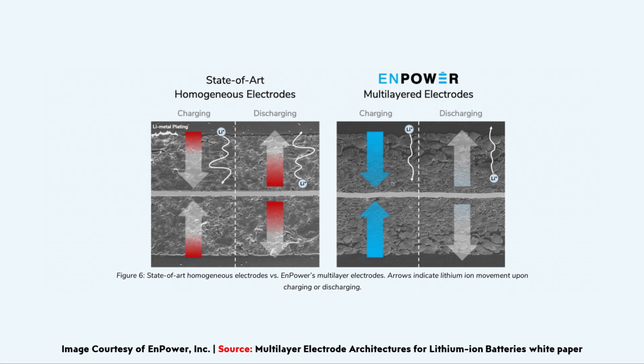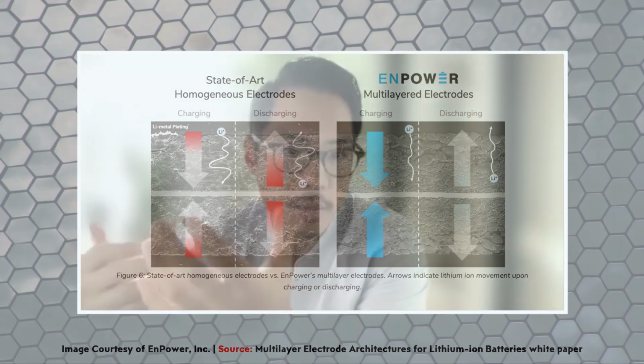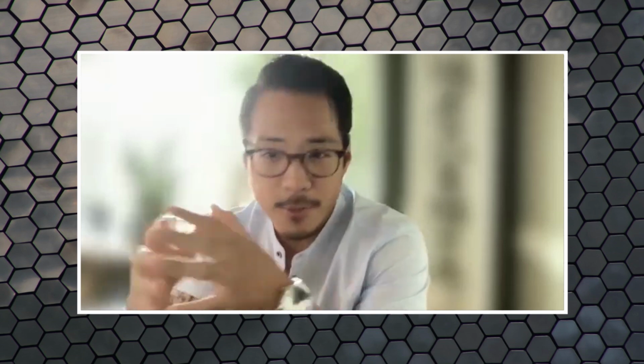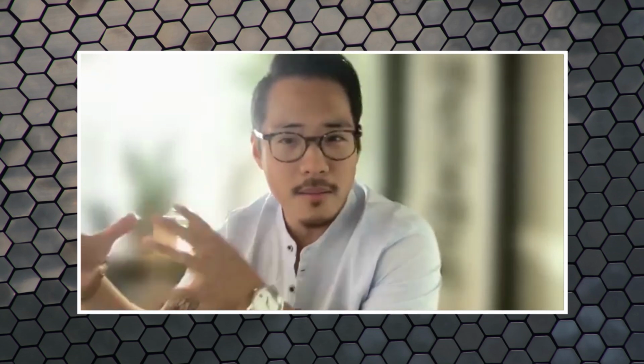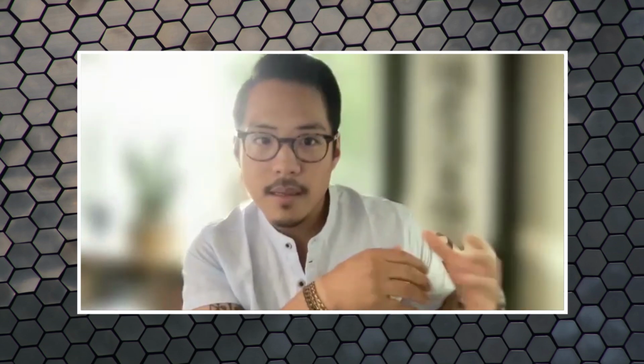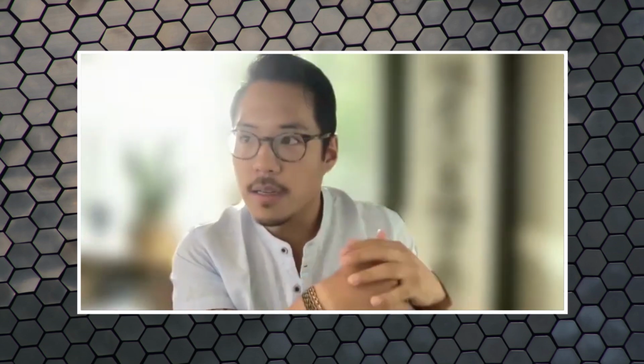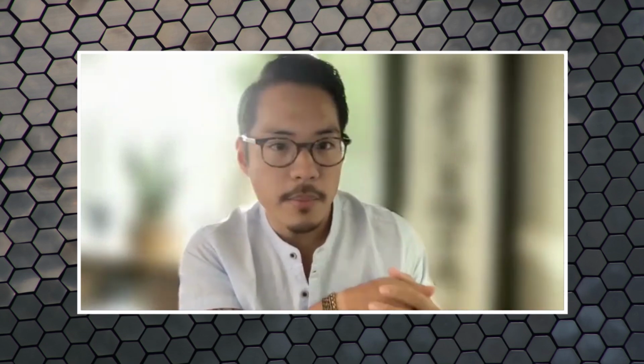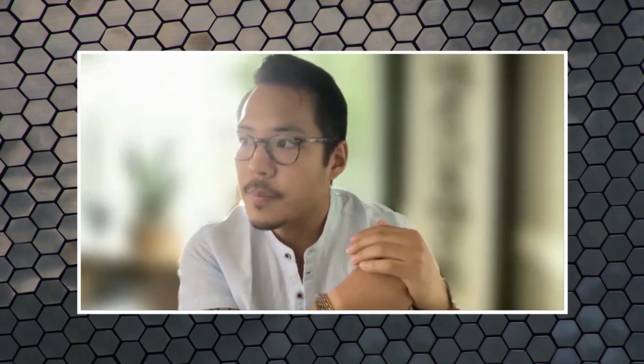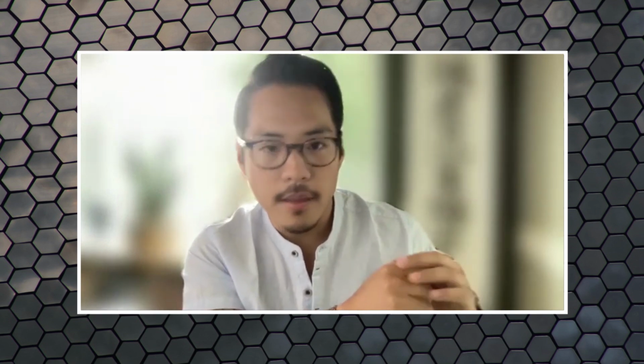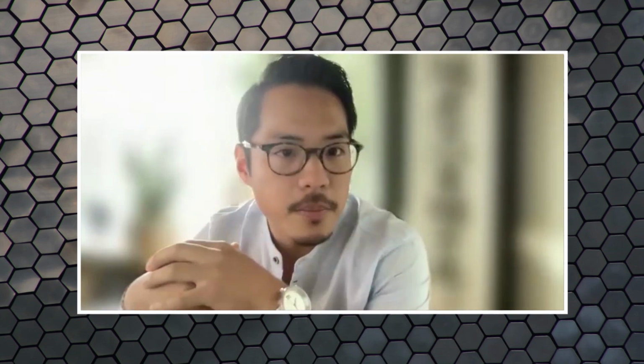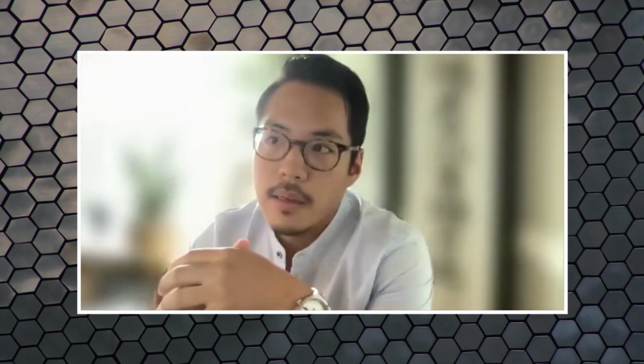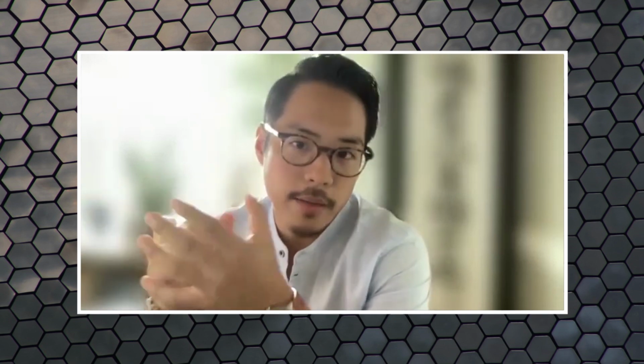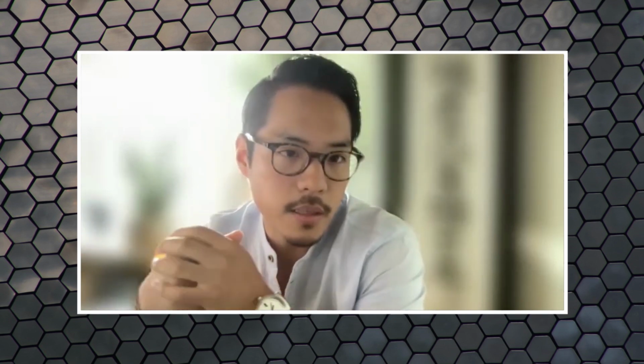So in this case, the anode in our conversation is graphite based. And the key risk in lithium-ion batteries is that, the reason why we call it lithium-ion batteries is that lithium metal batteries actually predated lithium-ion. The first batteries of this class were commercialized in 1989 by Moli, and they used a lithium metal anode. And of course, one of the problems with lithium metal is that you have dendrites form, and they also use a liquid-based electrolyte. So that eventually caused problems when they began short circuiting and resulting in some battery fires.